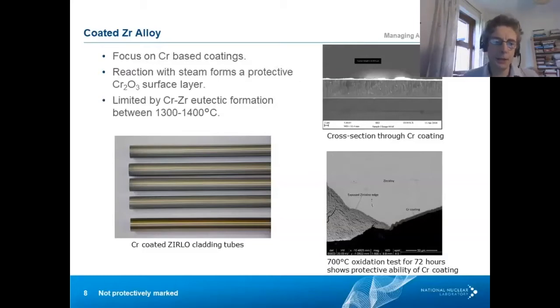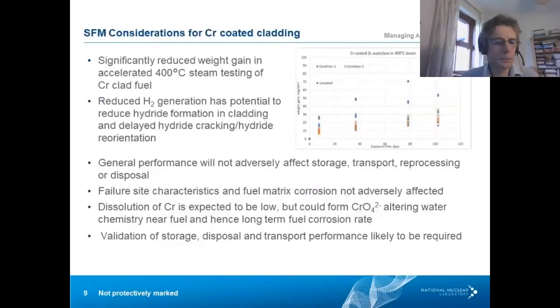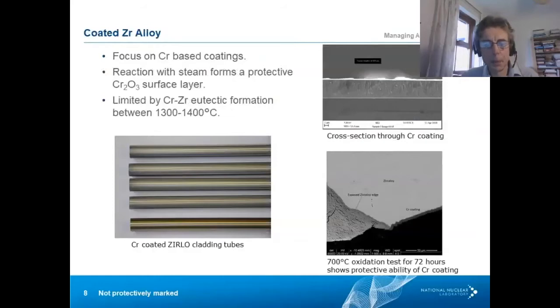The pictures you see here are of the chromium coated cladding in the bottom left-hand corner. In the top right-hand corner is a cross section, and the very bright layer at the top shows the thickness of the chromium coating, which is very thin but very well adhered. And the bottom right shows a more detailed example of the coating. And you can see immediately the effectiveness of the coating through this defect in the cladding coating that was deliberately left there to explore and demonstrate the effects of oxidation.